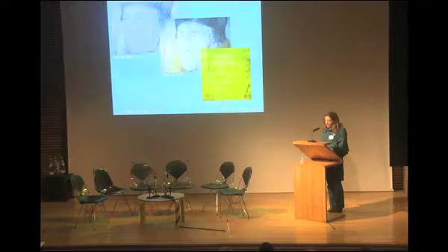Visual analysis has been comprehensive, involving examination with the naked eye and by microscope, using different light sources and directions of light, such as natural, raking, and transmitted. Raman spectroscopy, used for non-destructive and non-invasive pigment analysis, has been carried out on a number of Holbein portrait drawings and miniatures at Windsor, some results of which will be illustrated here. More recently, infrared reflectography has been utilised to confirm, or not as the case may be, the presence of silver point and where it may have been used, but this aspect is complicated and not yet fully resolved.